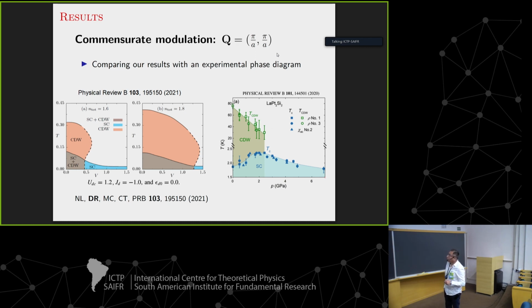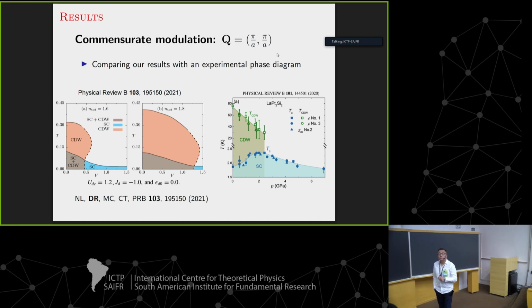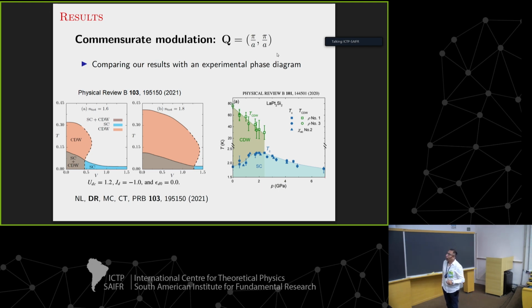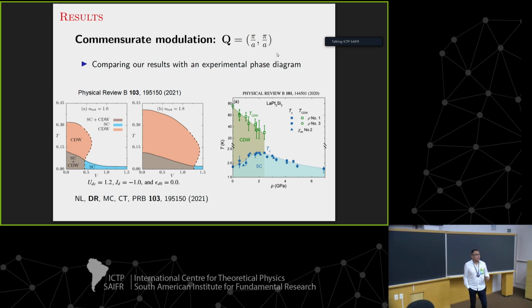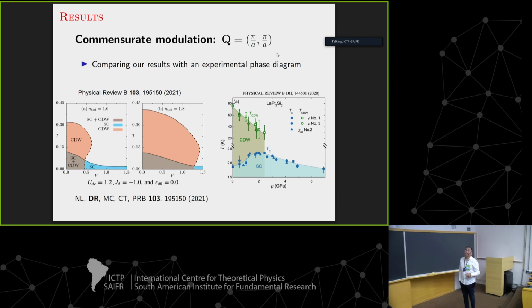If pressure increases, this CDW transition temperature decreases, and suddenly around maybe 2.4, maybe something like this, it suddenly goes to 0, indicating that a first order transition has occurred, okay? If the pressure increases even more, we see that the superconducting phase still survives, while the charge density wave order is completely suppressed. All right, these are our results, okay? This is published in this paper here, and you can see some similarities between these phase diagrams, okay? So from this similarity, we can conclude that our findings are at least qualitatively very similar or quite similar to the experimental results.